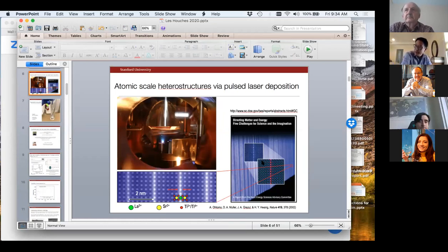Absolutely. So I think you're exactly right that if this is controllable, there's a very interesting opportunity there. I'm not sure that we can be comprehensively exact here, but at least we haven't ever seen this reorientation transition in the neodymium nickelate. Namely, we make the infinite layer phase, and if we go to longer and longer or higher temperature reduction reactions, we go from that to decomposition.